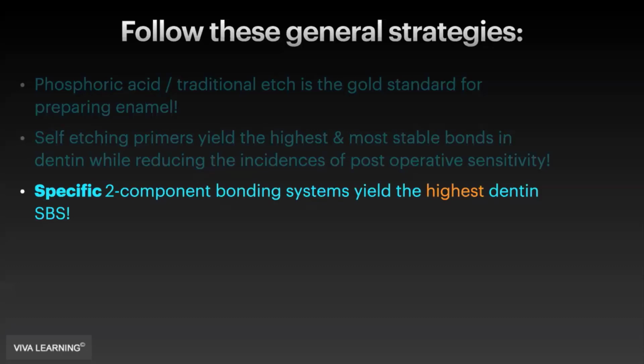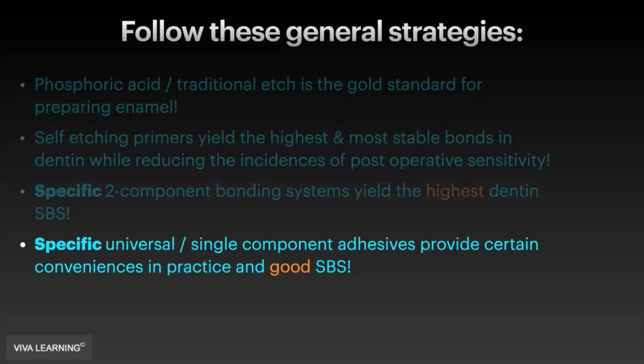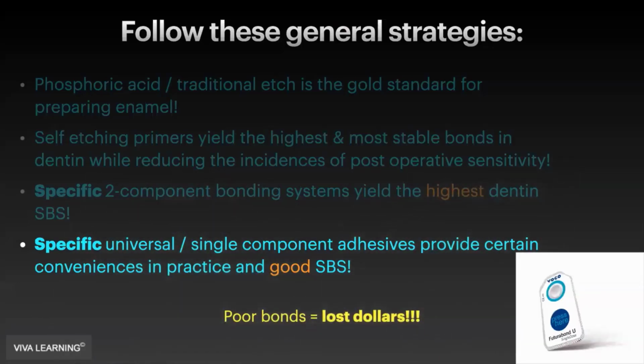The highest bonds on dentin we test are usually very specific two-component bonding systems, tested for shear bond strength. And then when we look at convenience, certain universal adhesives tend to give us not the highest, but pretty darn good bond strengths. And they do introduce a lot of conveniences as far as inventory and simplicity. So at the end of the day, poor bonds equal lost dollars.